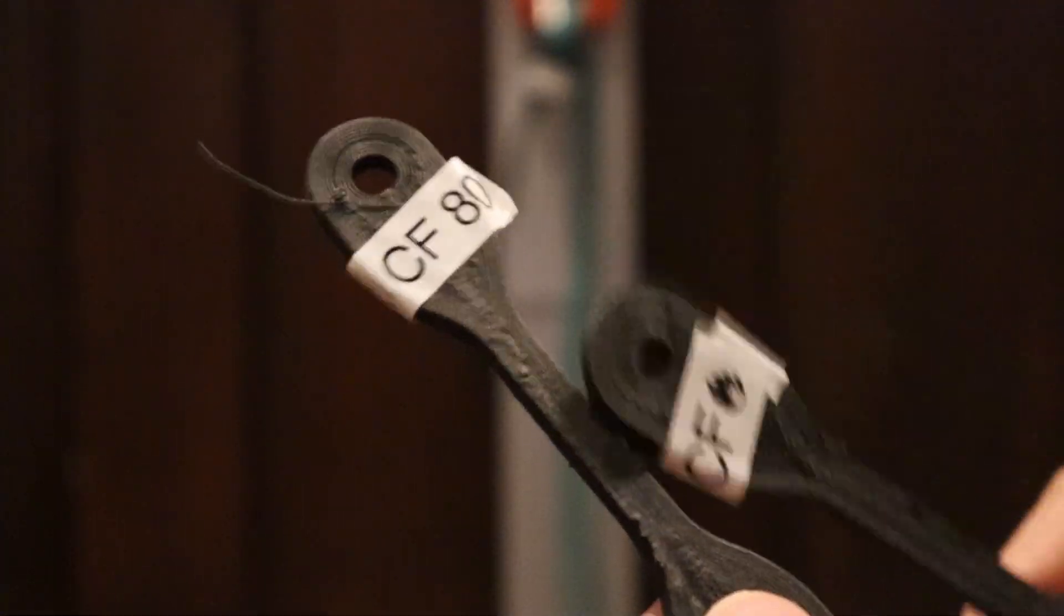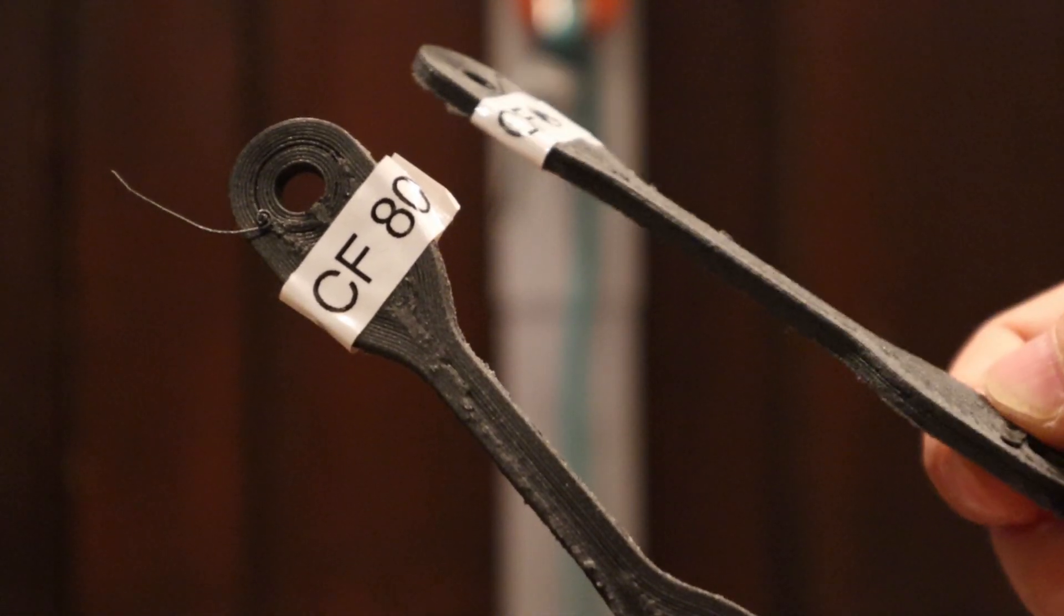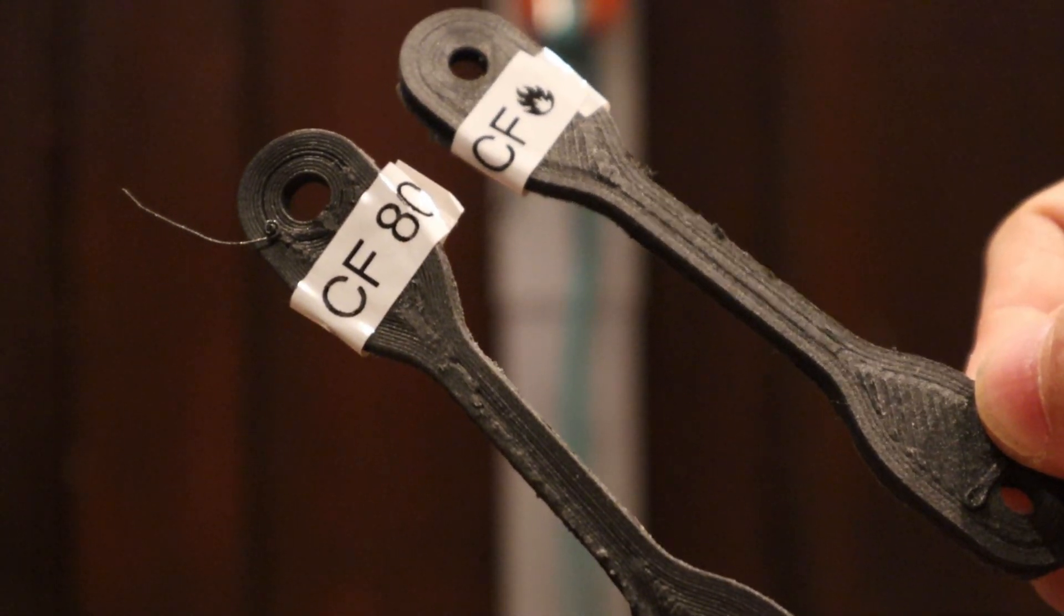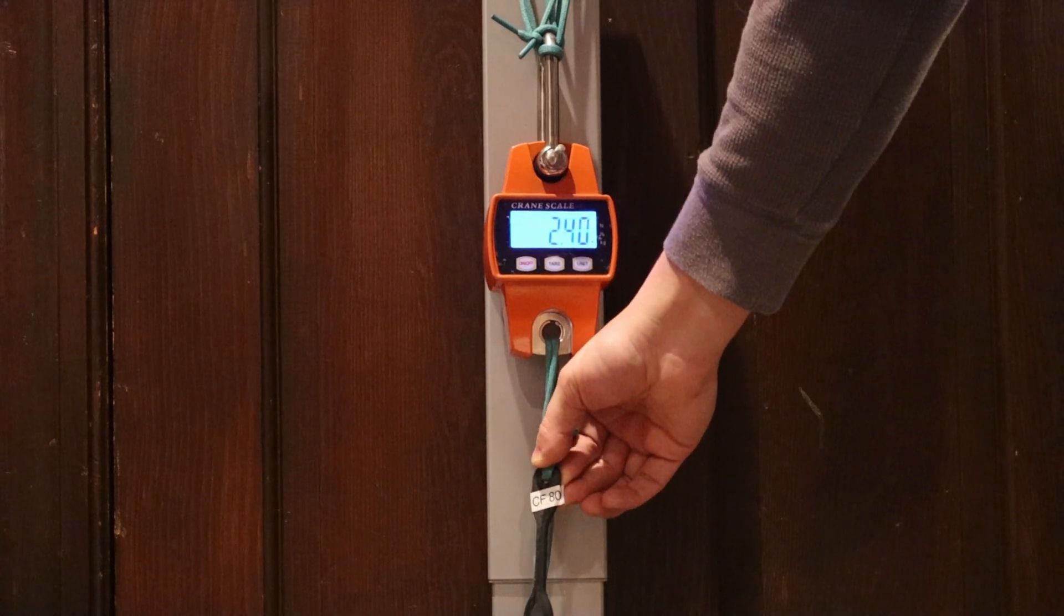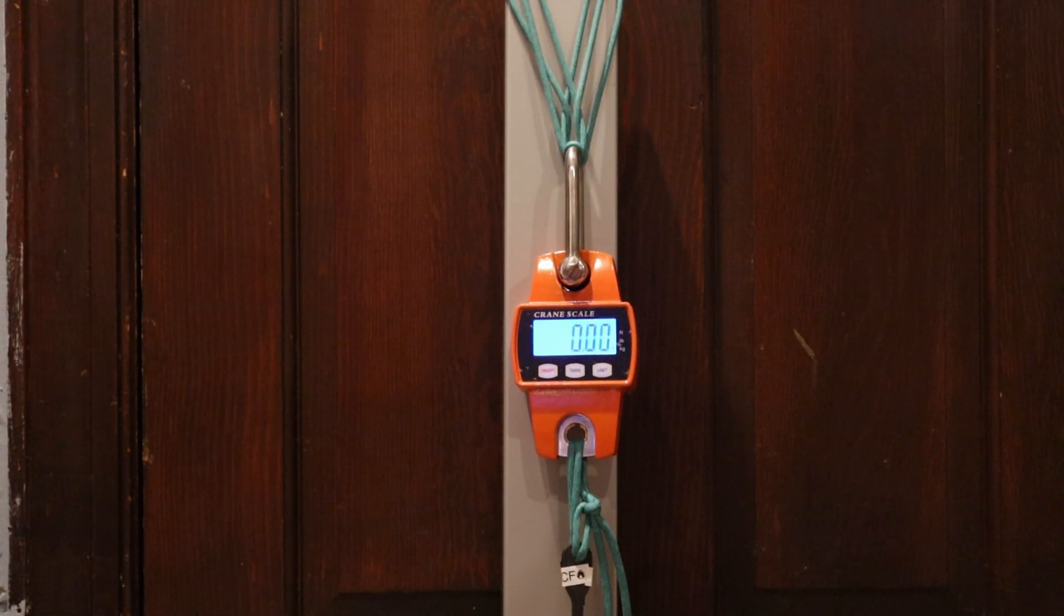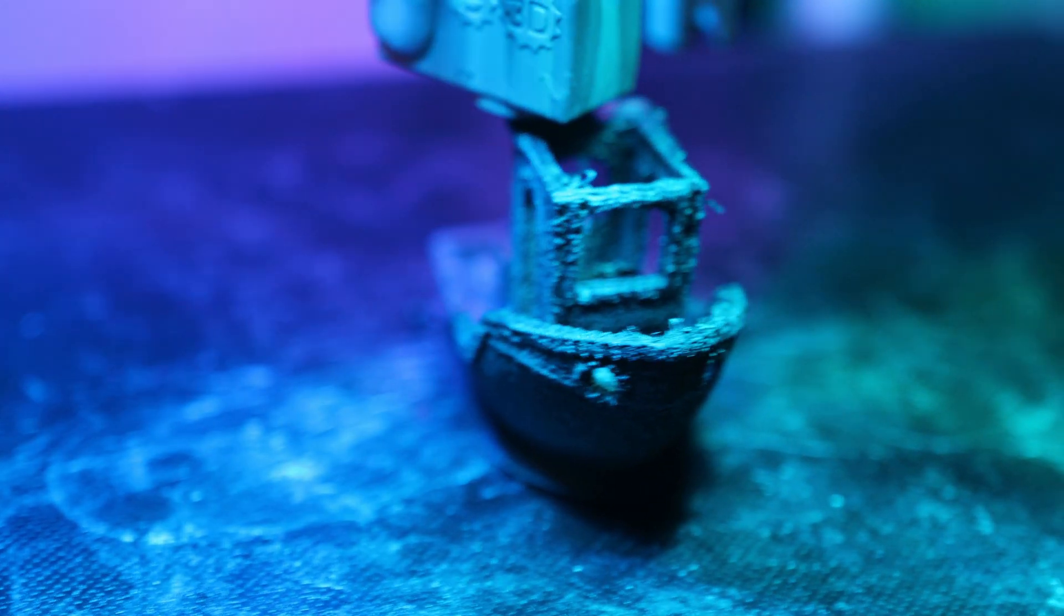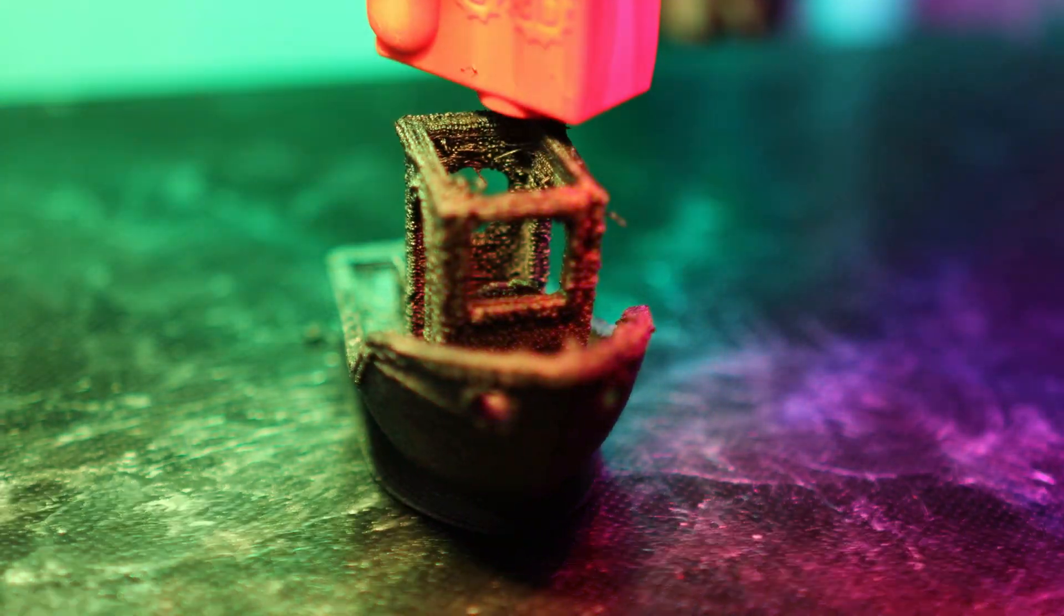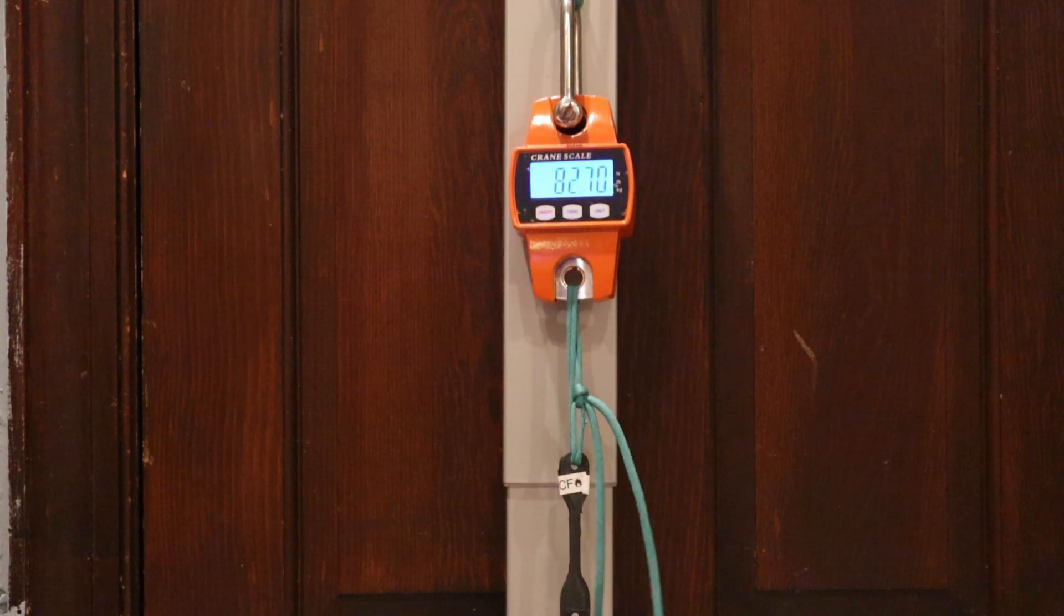To fix that problem, I air fried my carbon fiber, and then I was getting nice, clean, consistent extrusion. I was still printing at 100%, and if I measured this part, it would be more dense than either of these other parts that were printed in the wet state. I'll start out with this 80% density sample, and then I'll switch over to the material that was properly dried before printing. And we'll see what the difference in strength is between the two.